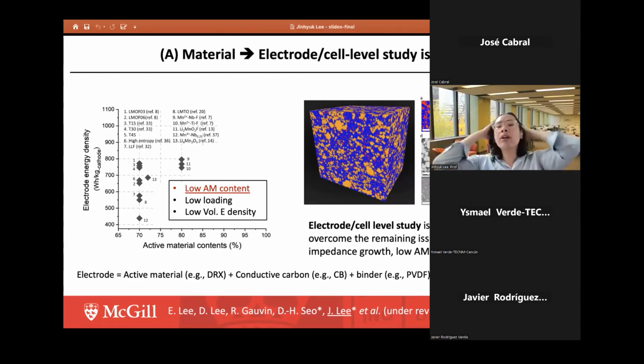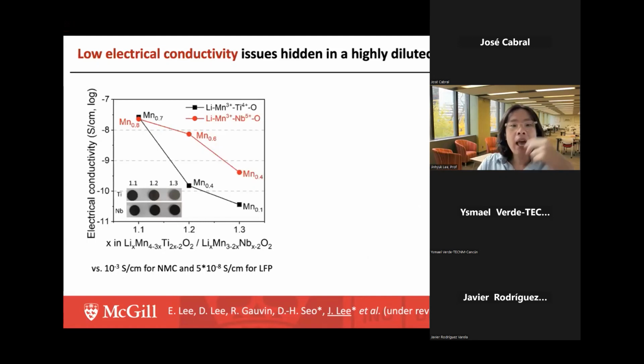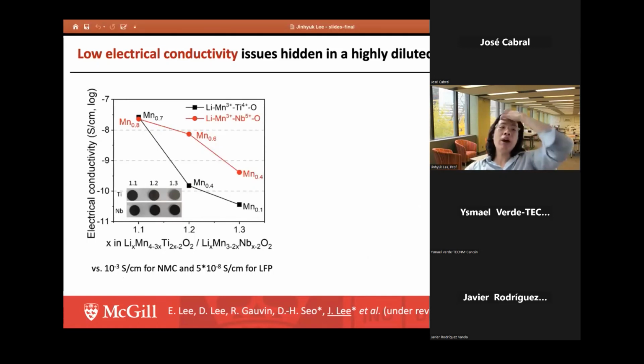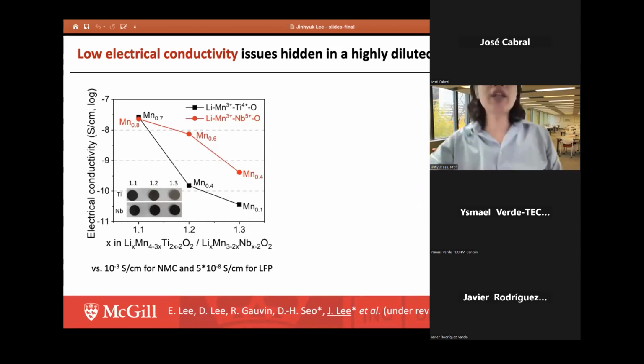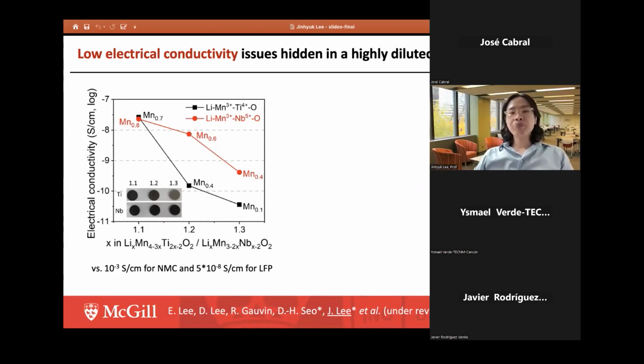So even if these materials deliver very high energy density per particle, because the content of the particles in the electrode is very low, you don't really get an energy density gain at the electrode or cell level, right? So we need to see what kind of issues will happen when this DRX material is included in a practical electrode and practical cell. We've been working on this practical electrode and cell level study. And what we found, although I never discussed it in the previous slides, is that the electrical conductivity of these DRX materials tends to be much poorer compared to traditional cathode materials. This caused a lot of problems when we tried to increase the active material content to a practical electrode composition. For example, here I'm showing you the electrical conductivity for many different types of lithium excess DRX compounds.